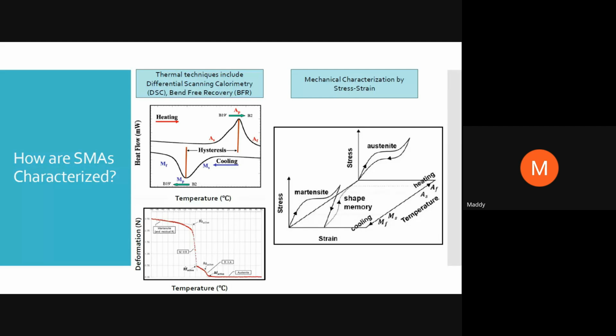So the starting and the finish temperature of the austenitic start or the martensitic start, they are not aligned and there is a shift. I didn't mention it, but I call it the hysteresis. And that's because you have grain boundaries, you have dislocations and a bunch of other things, it could also be precipitates, that are preventing the transformation from occurring at the same temperature. So what happens is you need to expend more energy when you are heating it back. On cooling, the amount of energy required is much lesser. So that's why there is a hysteresis, and that's why they are not matching.